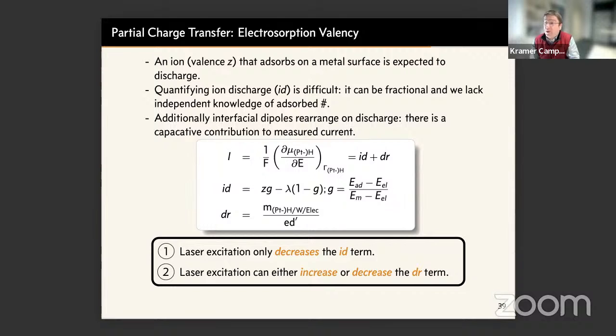So we think it's quite clear the whole thing is reproducible. We think it's quite clear from the sign of the signal that we see that we do not drive reduction or oxidation with this laser pulse going both ways. This is inconsistent with the sign of the effect that we see.